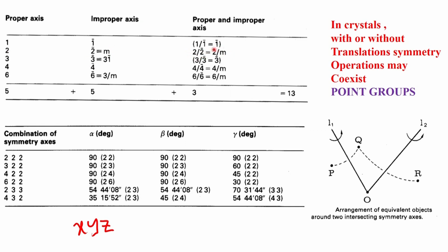So, this is an additional point group symmetry which is illustrated. So, this now becomes a new point group where x y z will now go over to, first there is a twofold operation which will take it to minus x y minus z. Then on the x y z we will also operate a mirror symmetry. So, it becomes x y bar z.